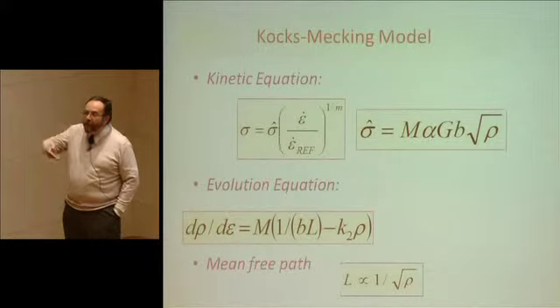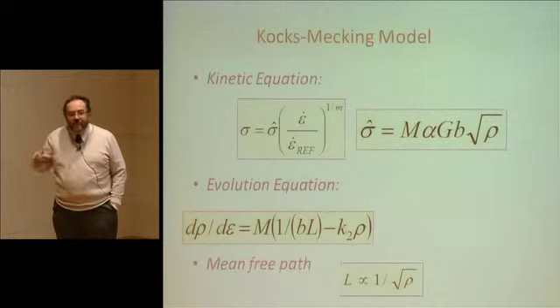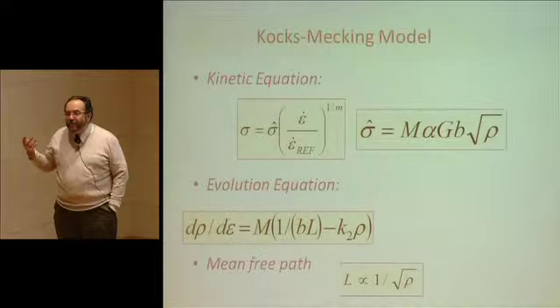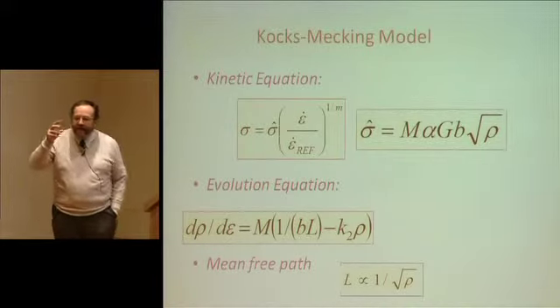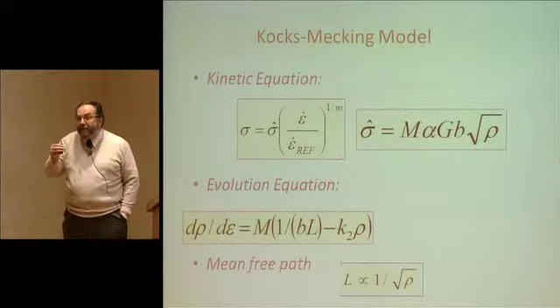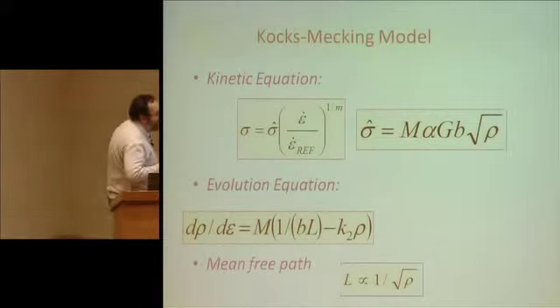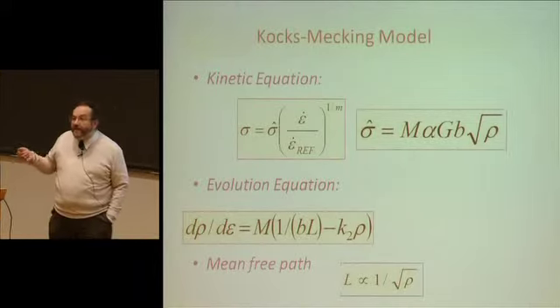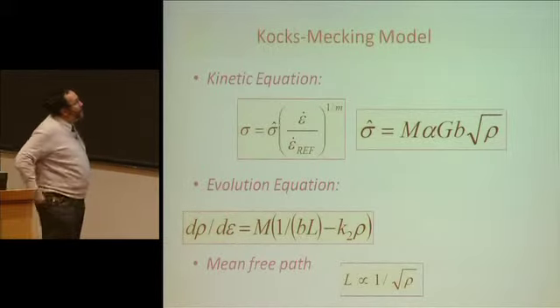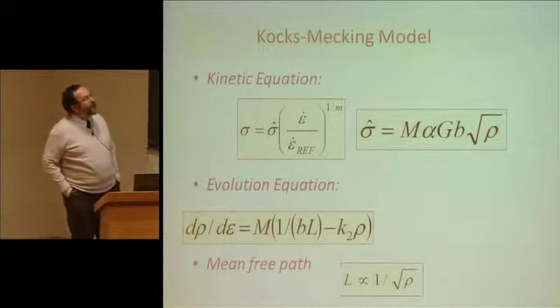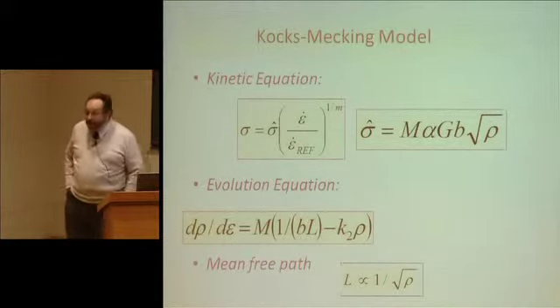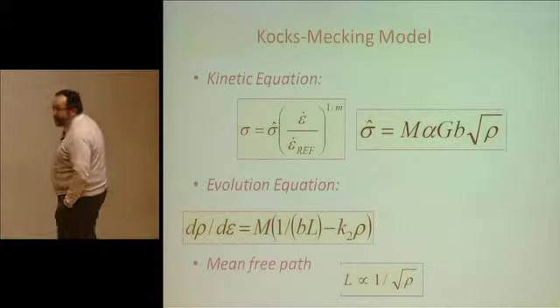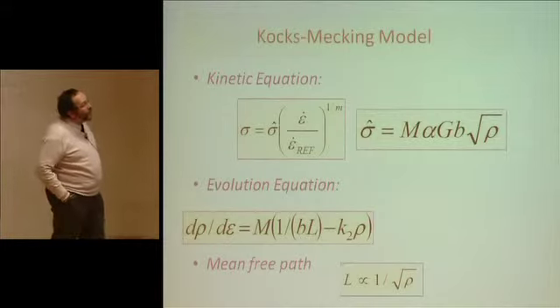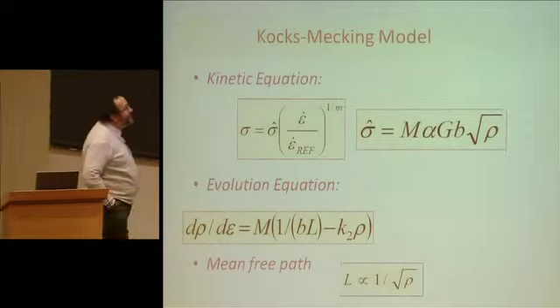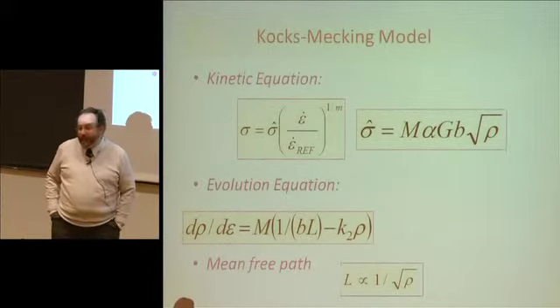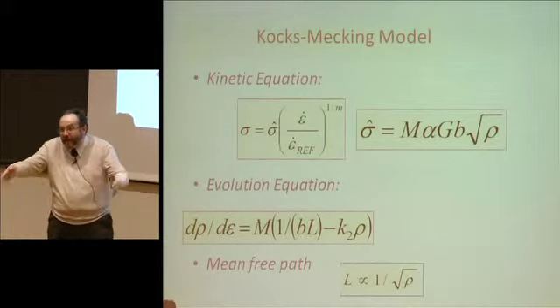And this intrinsic resistance is that of the crystalline network, but as you are deforming the material, you're accumulating dislocations, which increases the material's resistance. So the Kocks-Mecking model is designed to normalize the constraints you're applying based on the resistance of the material, which itself is connected in a pure metal to the dislocation density within that material, which is the meaning of this first equation: the constraint normalized by the reference constraint, sigma with a circumflex, must be equal to the speed of deformation normalized by the reference speed of deformation. And the idea is that the reference constraint is the square root of the dislocation density.